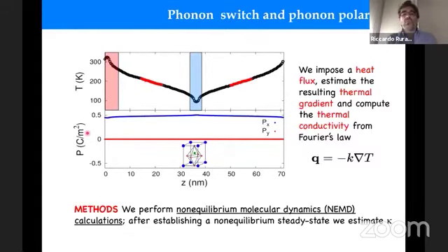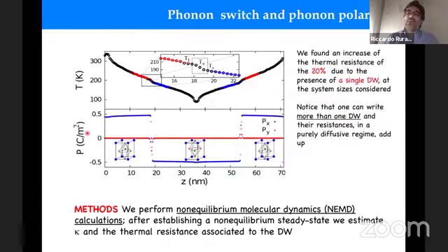Good. So now we can write our domain wall. This is easy to see now in the lower plot. You see here we have the distortion up, and here we have the distortion down. So the polarization goes from plus 0.5 to minus 0.5, and you see the transition is rather abrupt. The polarization entering the screen is always 0, and it has a small glitch, as predicted by the theory, at the domain wall, at this boundary that we have written.